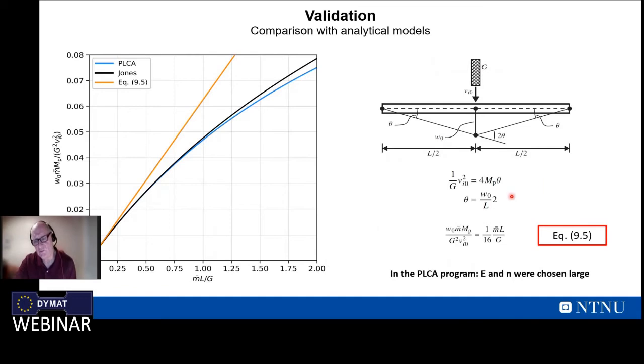comparison. If you want to be a real engineer, you don't use this mode approximation technique. You say that, for instance, you have a clamped beam and a dropped object, you have the kinetic energy, which is then absorbed as plastic energy in a hinge here and hinge here. Then you can put up this, plot it, and then you see this is the line here. So when the mass ratio is 1, you definitely get a very conservative solution. If you want to be a little bit more accurate, which maybe can be the case for you, then you should, for instance, try to use this mode approximation technique.